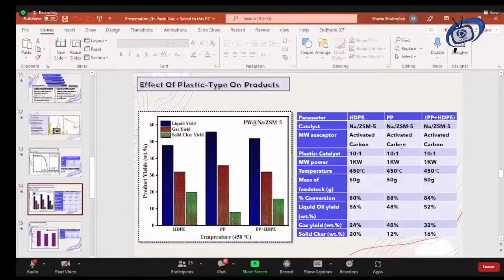And if our focus is on the production of the gases, we should choose the PP because it gives us 40% of the gas, which is much higher as compared to the others. And the HDPE gives us 20% solid residue, which is much higher as compared to the pure PP and its mixture with HDPE.